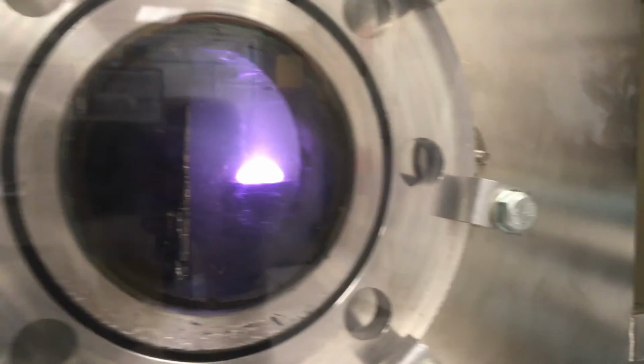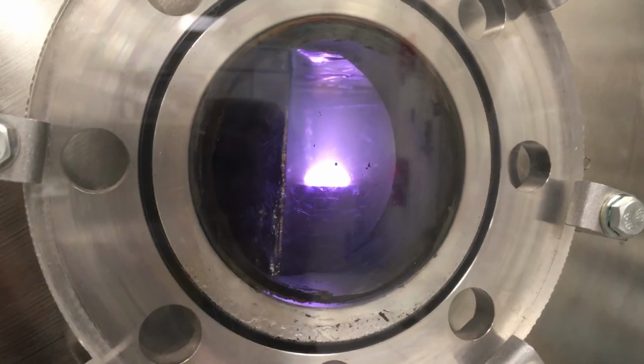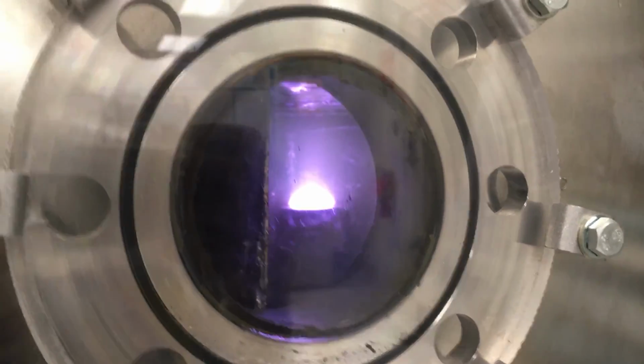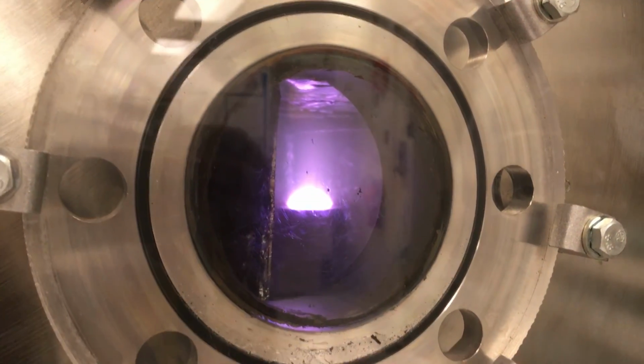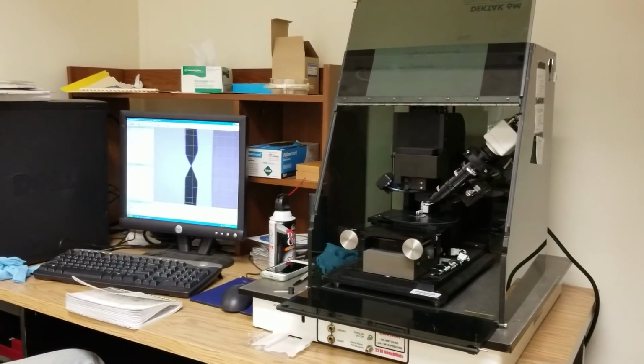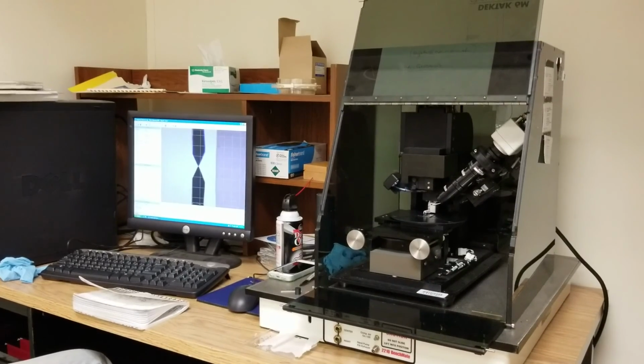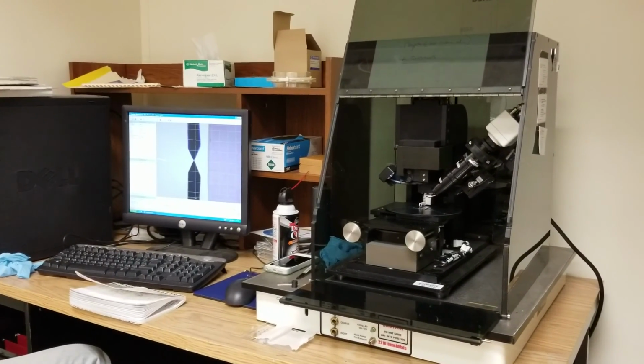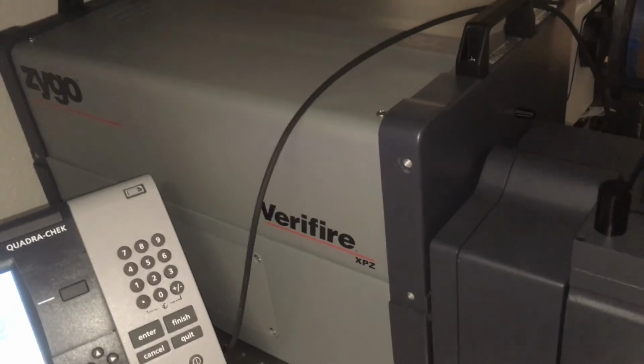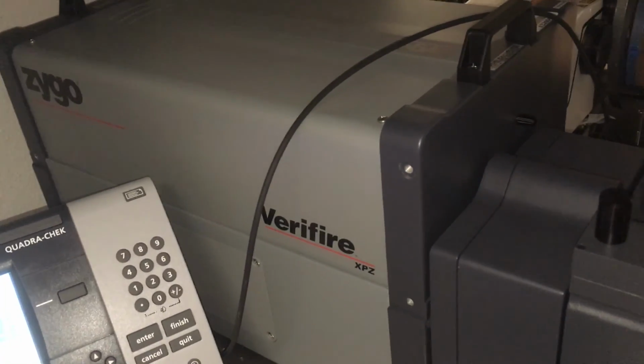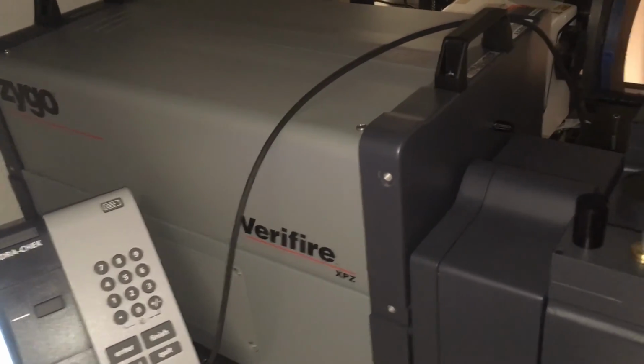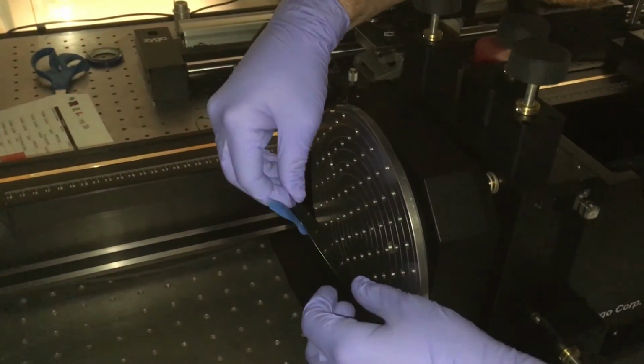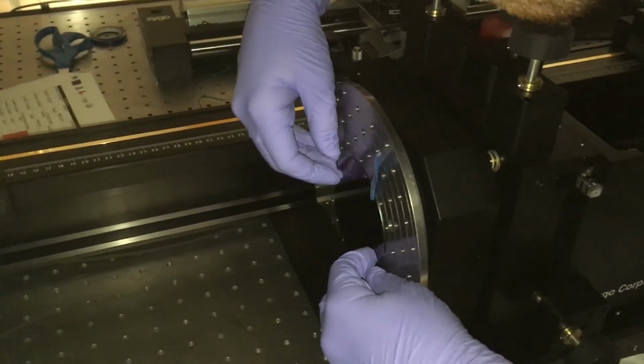Here we are sputtering the target material onto a sample so we can measure the deposition rate to calibrate our future depositions. This is us using a profilometer to measure the deposition rate off our sample material that we deposited on. This is the Zygo XPZ interferometer that we are using to measure the stress in the silicon wafers, which, as you can see, Nick is mounting onto the mount.